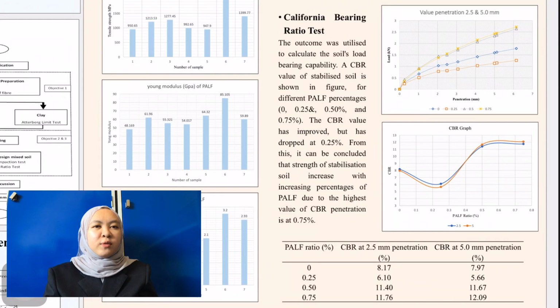The CBR value of the stabilized soil is shown in the graph for different pineapple leaf fiber percentages, which are 0, 0.25%, 0.5%, and 0.75%. As can be seen by the curve, the CBR value has improved but dropped at 0.25%. From this, it can be concluded that the strength of stabilized soil increased with increasing percentage of pineapple leaf fiber, due to the high value of CBR penetration at 0.75%.